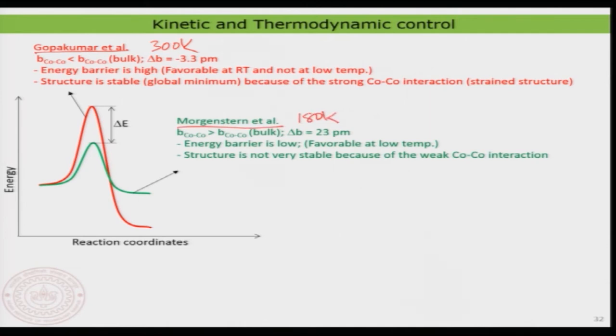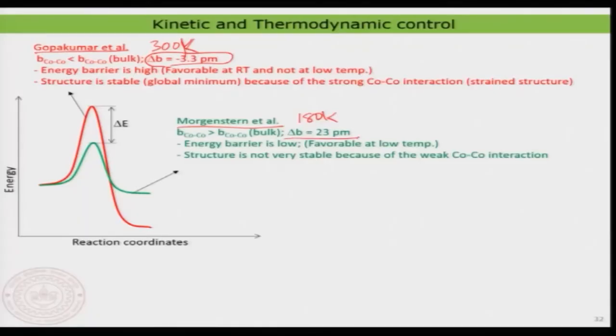Now, just to put everything in summary, in the first example, you can see that there is a compression of about 3.3 picometer of the cobalt-cobalt lattice at the interface. In the case of the second example, there is an expansion of about 23 picometers for the cobalt-cobalt distance. Now, one would naturally ask, which one is the most favorable?